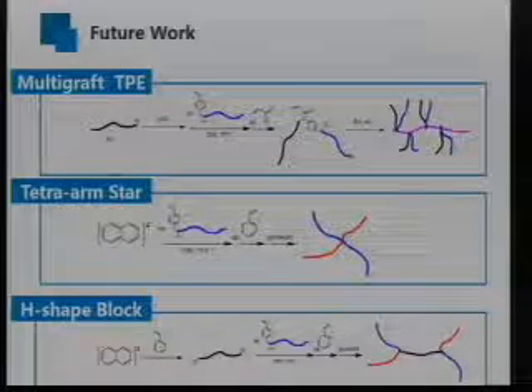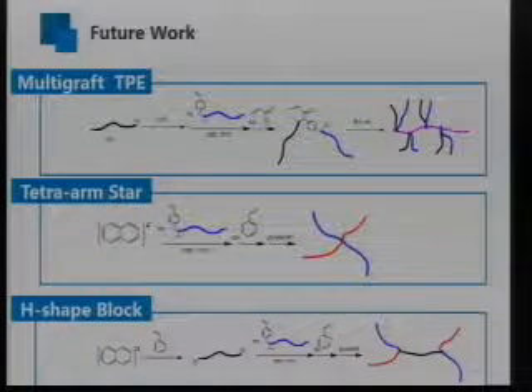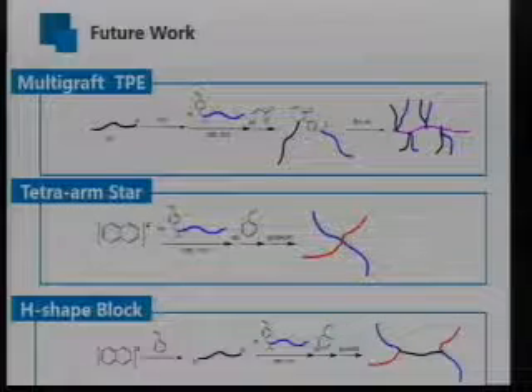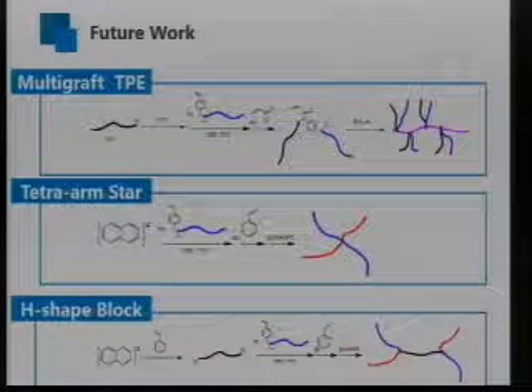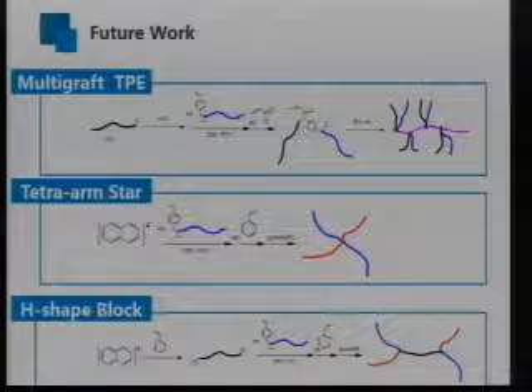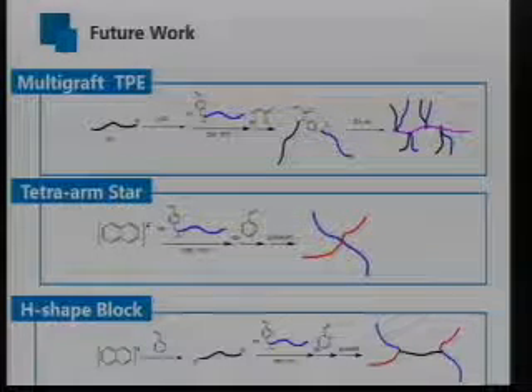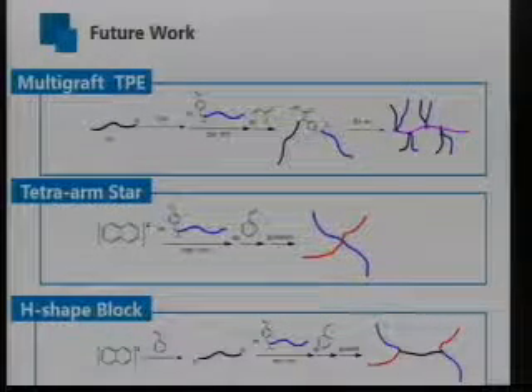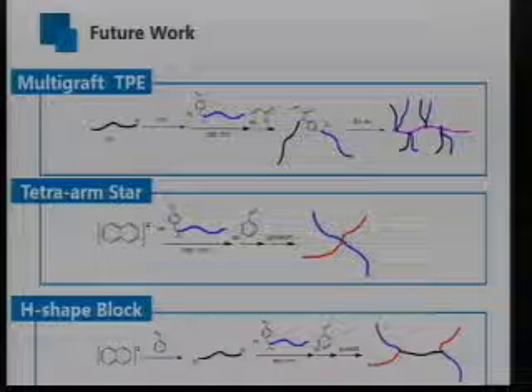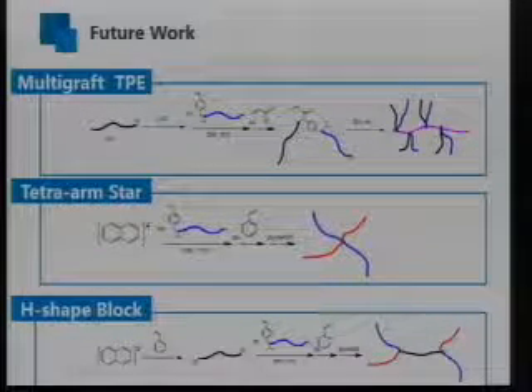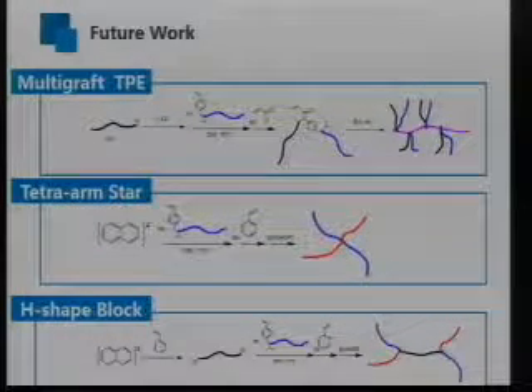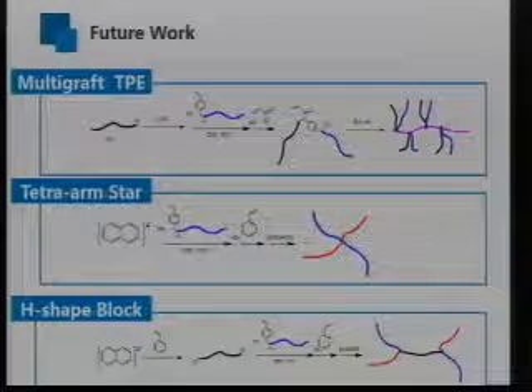When we use difunctional initiator to couple the macromonomer first, followed by the growth of the second kind of monomer, these tetraarm stars can be polymerized. If we use the difunctional initiator to polymerize styrene first, followed by the coupling reaction and the growth of another monomer, this kind of H-shaped block polymer can be synthesized.